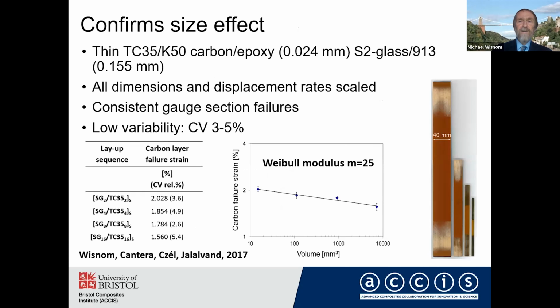So we applied this for looking at size effects. So we did these scaled specimens where all those specimens are hybrids. So they've all got carbon in the middle and glass on the outside. And again, we've doubled all the dimensions, thickness, width, and length. We didn't use tabs on these. We just tested straight in the test machine. And we got consistent gauge section failures. And again, we got a result which fitted on a Weibull modulus, showing a reduction in strength as you increase the size, and in this case, a Weibull modulus of about 25.